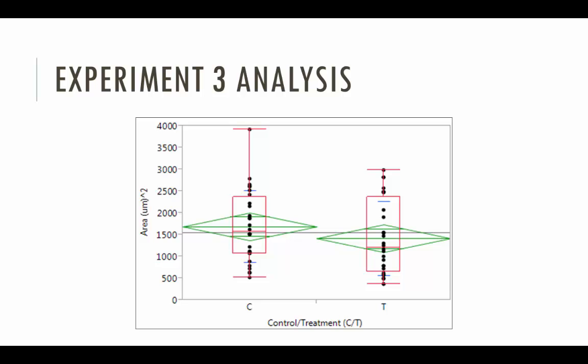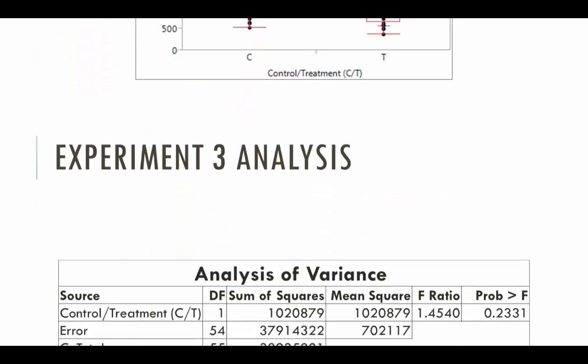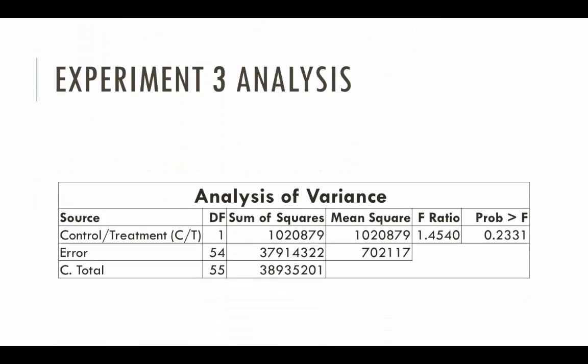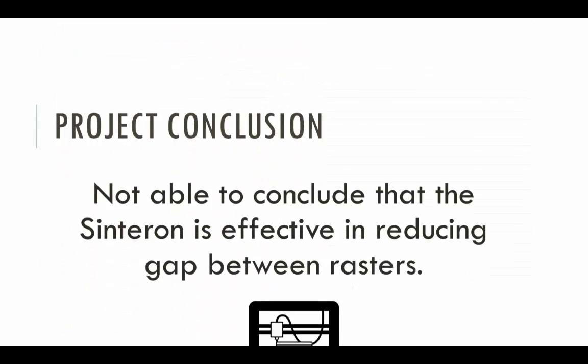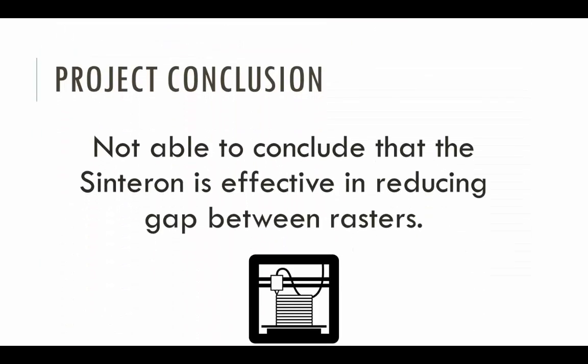The treatment sample group had a smaller average mean. The ANOVA table gives us a p-value which was greater than 0.05, so we couldn't conclude that the sample groups were statistically different from one another. In conclusion, the Sinteron was able to heat up the surface layer of the print, but the Sinteron was not successful in reducing the gap between rasters. All of the experiments concluded this result.